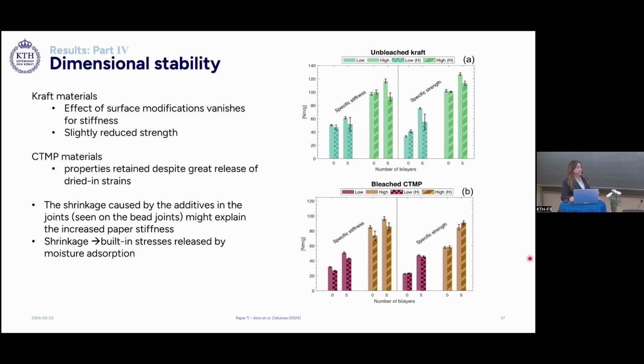The shrinkage caused by the added LBLs, which is seen in the bead joints, might explain the increased paper stiffness. And since we have shrinkage, this means that there's built-in stresses which are released by the adsorbed moisture. And in the case of the kraft materials, which have a softer fiber wall, which will induce a larger shrinkage and therefore a larger effect on the stiffness.